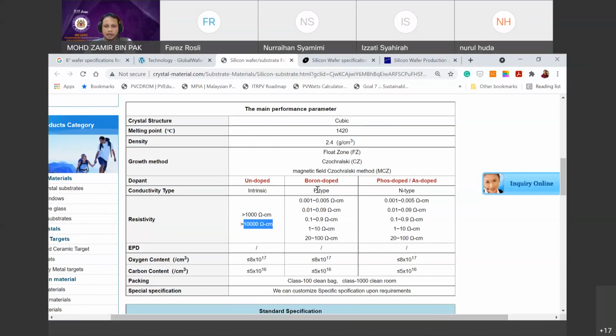If you, on the other hand, have p-type, well, it ranges across different resistivities. It can be from very low resistivity, like 1 times 10 to the minus 3, or 5 up to 5 times 10 to the minus 3 ohm cm, and it can also be up to 20 to 100 ohm cm. So if you see this, for example, let's just recap a few things. If you see this p-type from 0.001 down to 20 ohm cm kat bawah sekali, which wafers are lightly doped? Which category is lightly doped? You can unmute yourself or write down in the chat box. 20. 20 apa? 20 ohm cm, lightly doped.